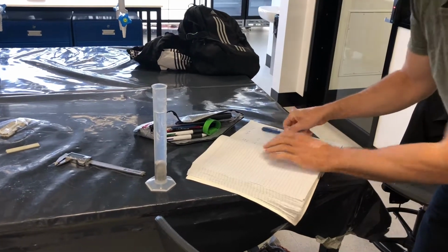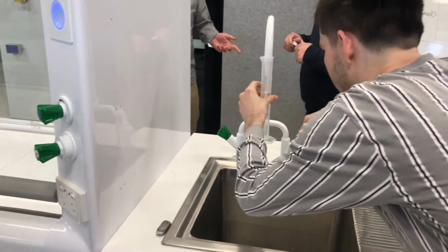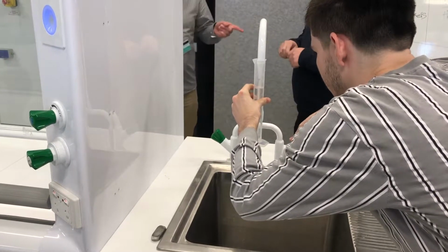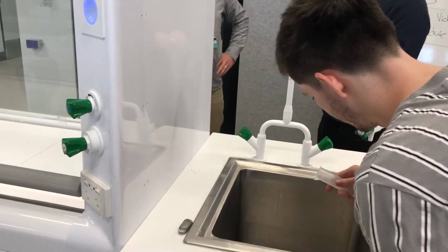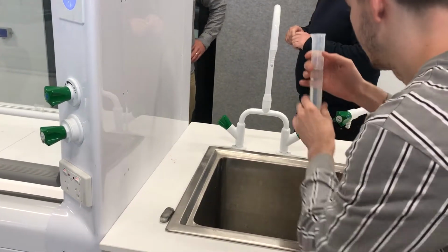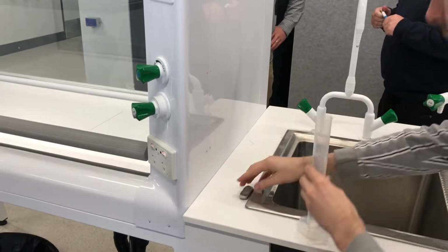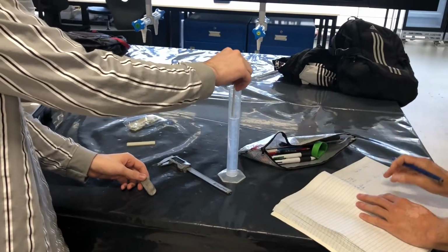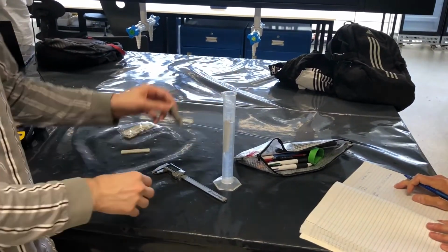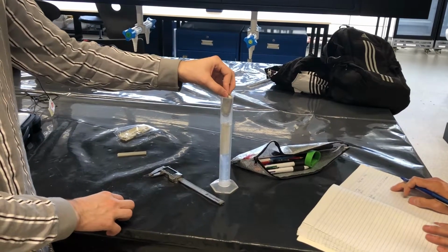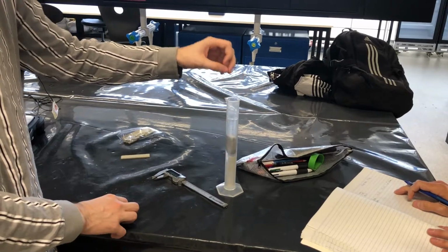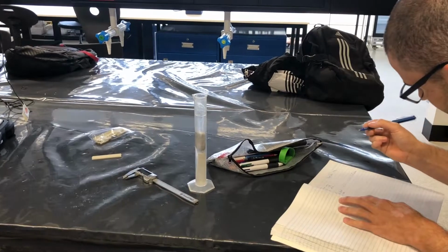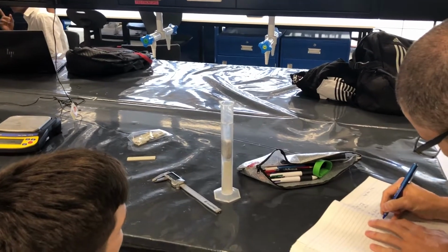The second step was to measure the volume of our sample by placing the eraser on top of the sample inside the beaker. The measurement beaker had 80 mils of water. The water displaced to 97 mils when the eraser was placed on top of the sample in the beaker. 97 minus 80 equals 17 mils of water. Subtracting the volume of the eraser from the measured volume gave our sample a water displacement of 5 mils and a volume of 5 centimeters cubed. Using the density equation, our sample had a density of 880 kilograms per meters cubed. The average measured density of our sample was 892.7 kilos per meters cubed, with a standard deviation of 12.7.